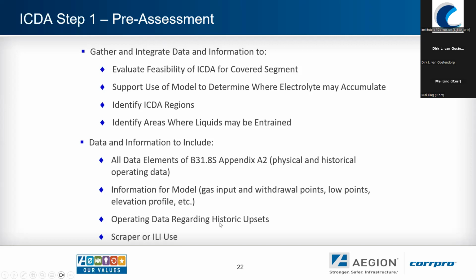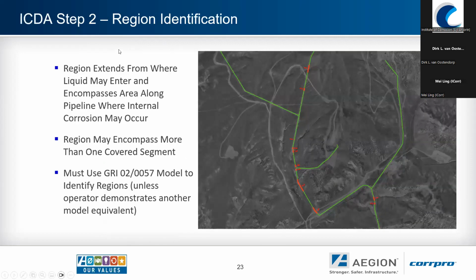Operating data, especially if we're talking about what would be a normally dry gas pipeline, as far as the frequency and magnitude of any upsets on the dehydration system or any changes that have occurred. And then if there is any scraper ILI use in the past, as far as previous data that could be helpful. All of these pieces get blended in together to develop the process and allow the fullest analysis using the internal corrosion direct assessment. So the region identification then is another issue, as I mentioned before, because the federal regulations focus mainly on the high consequence areas or now moderate consequence areas. So although you may be working across an entire pipeline section, there may only be specific areas where you need to have this level of detailed information.